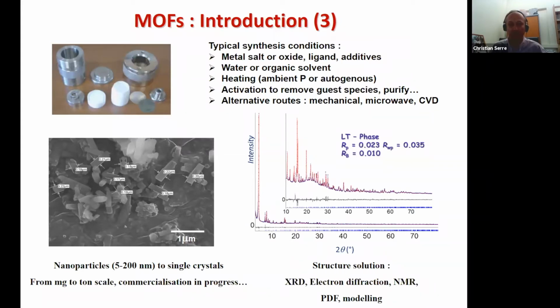And of course, with MOF, if you want to exploit the porosity, you need to remove what is inside the pores. And it is not as simple as it looks. With zeolite, you can calcine, and then it's done. Your material is highly thermally stable. With MOF, they are more fragile, less thermally stable. So you need to remove everything that is inside the pores, the solvent, but also sometimes the ligand or some salt. And this is critical.